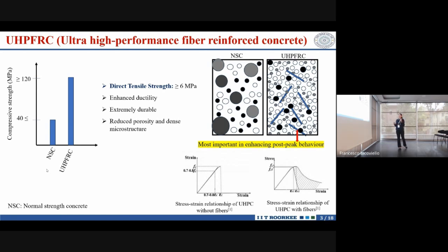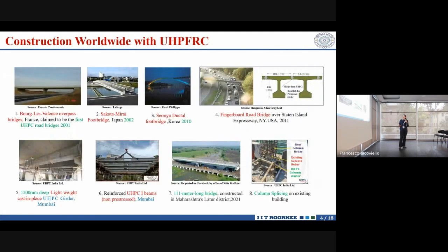And as far as the ductility is concerned, the fibers are the most important part in this study. The fibers are the ones that will improve the toughness and reduce the brittleness of the material, as you can see here. Without fiber, there is a brittle behavior, but with fiber, the post-cracking behavior is significantly improved. So in this study, we are focusing on how varying fiber percentage will affect the post-cracking profile of the material. These are the constructions that have happened worldwide, gaining a lot of traction these days.